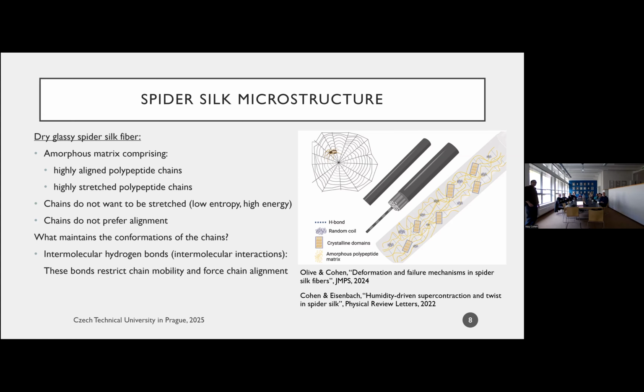The way this happens is because each of the chains inside the silk fiber interacts with its neighboring chains through a series of intermolecular bonds, specifically hydrogen bonds. Each chain is connected to its neighbors with a series of hydrogen bonds, and these bonds act as local constraints that restrict the mobility of the chain. The chain wants to explore different conformations in space. It wants to wobble around, but these bonds do not let it do that. So the chain is pretty much fixed in space. Because of that, that enforces alignment and this configuration of the chains.